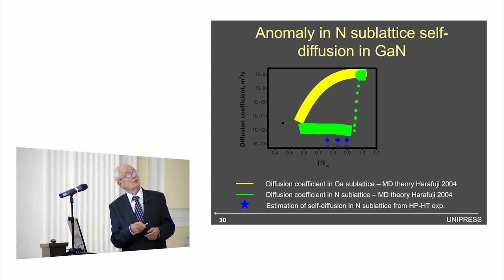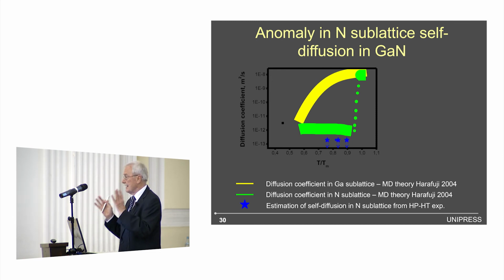This is the picture which shows that the diffusion in different sublattices, in the sublattice of nitrogen and gallium, is completely different. You see the diffusion in the nitrogen sublattice does not depend on temperature up to melting. So there are no vacancies which would be created in this sublattice. The vacancies are created only in the gallium sublattice.